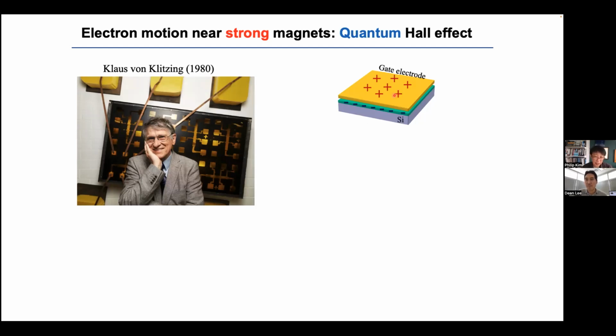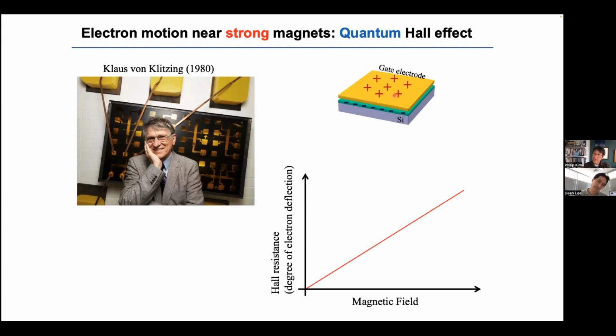That's when this person, Klaus von Klitzing, applied the magnetic field to this two-dimensional silicon and did the Hall effect measurement again. Quite surprisingly, you see the Hall effect appear, but not in a continuous way; it's discontinuous. This discontinuity is rather surprising. In fact, it is so well established that it's almost a so-called quantized step. Out of this, within 5 years, he also got a Nobel Prize. Now, to explain why such a discrete step appears in the Hall effect, we have to look through the physics again, the quantum physics, as you can imagine.